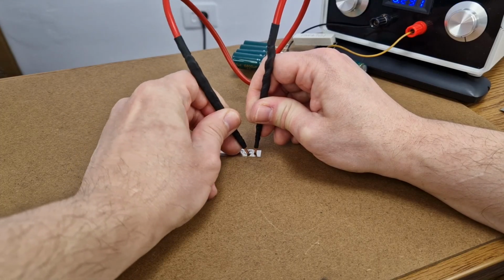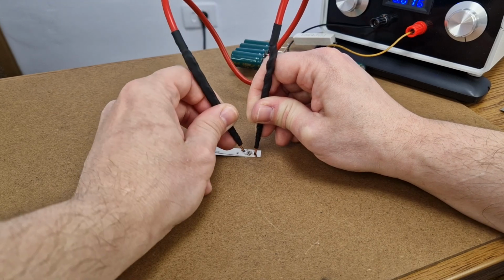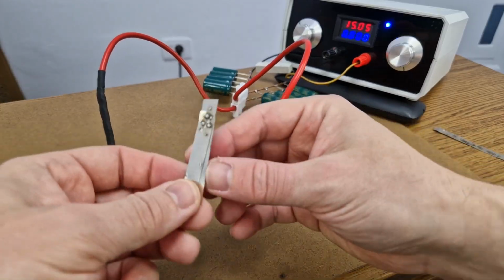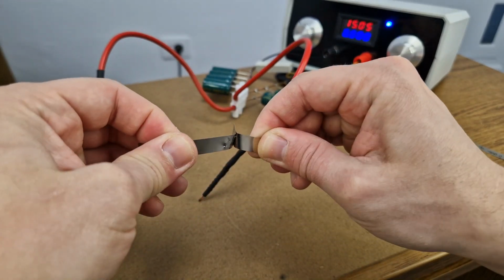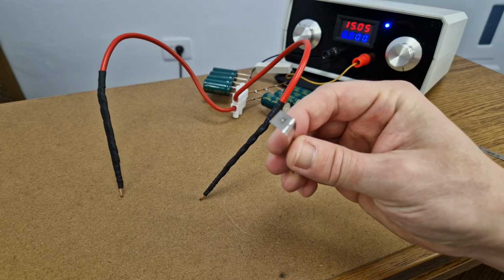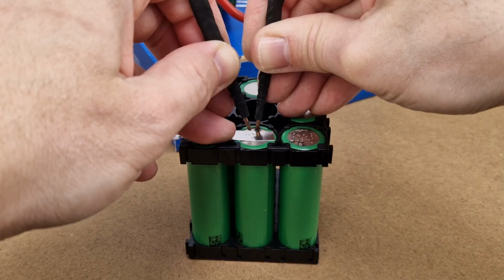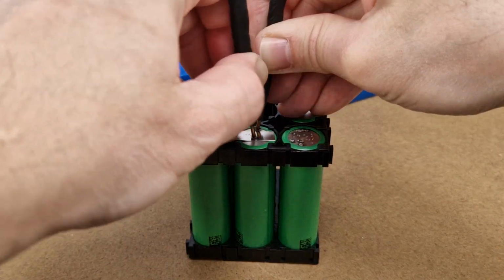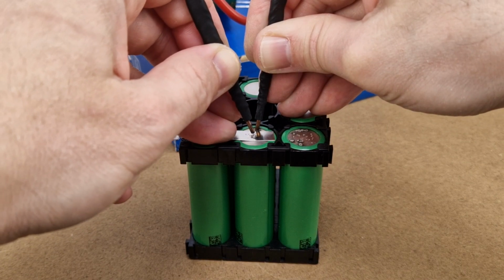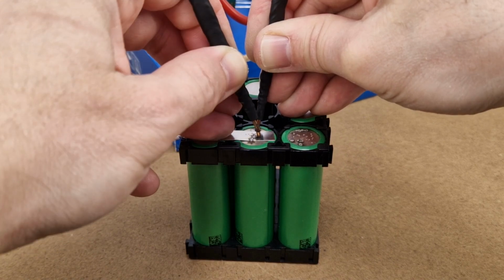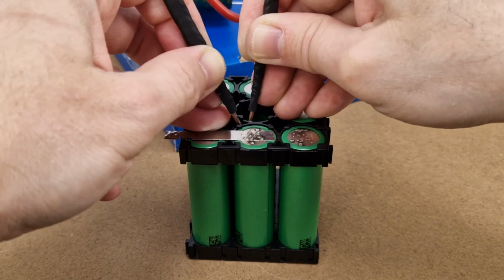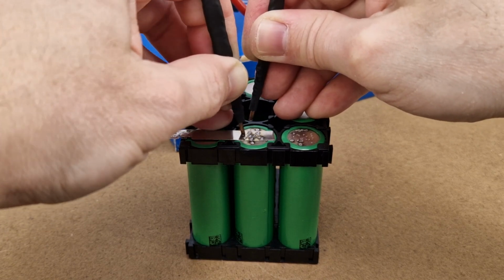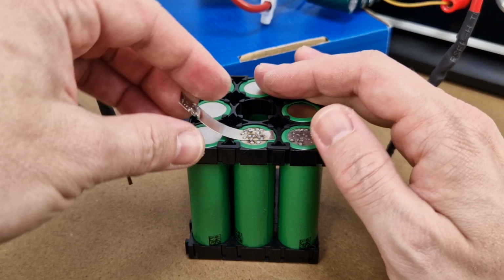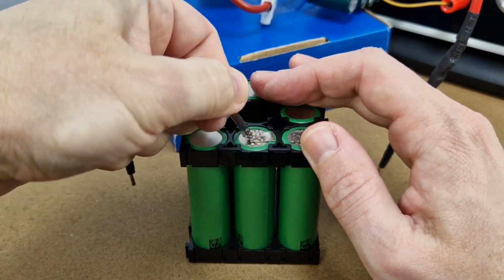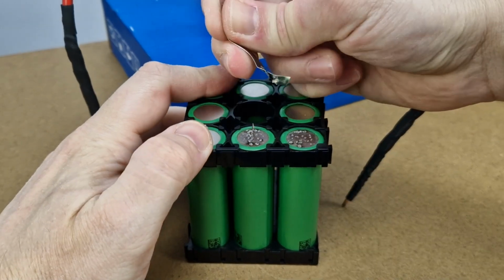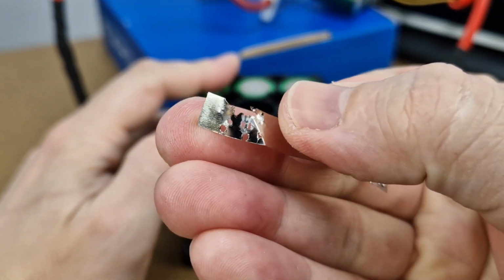Let's try to weld together two nickel strips of 0.15 millimeters. Hey, looks like the nickel strips are almost welded together. But the most important thing is, will it be able to spot weld nickel strips to lithium cells? Well, after a few unsuccessful tests with different types of nickel strips and different voltages, I managed to get some powerful fireworks with 18 volts and 0.1 mm thick nickel strips. The strip appears to be welded, but can be removed without much effort.